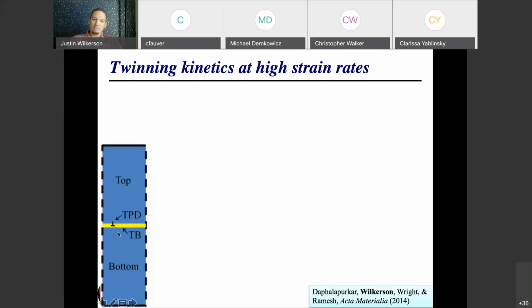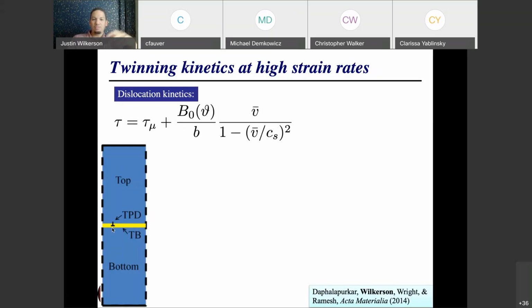A simpler mechanism is that there is a so-called twinning partial dislocation on the twin boundary itself, and you can just move that twinning partial dislocation along the twin boundary, and that's going to facilitate the motion of the twin boundary itself. Okay, so then what you end up getting is that the motion of the twin boundary, its kinetics, are just governed by the kinetics of the twinning partial dislocation and then the spacing of twinning partial dislocations along the twin boundary itself.